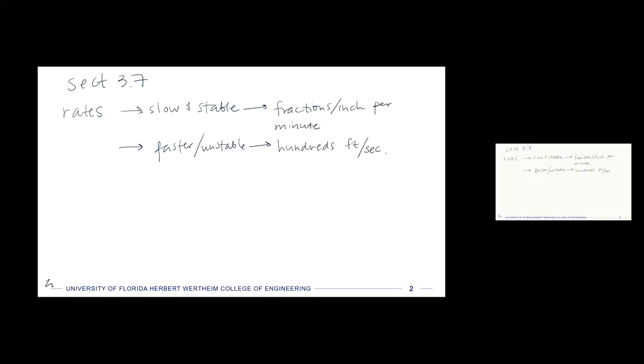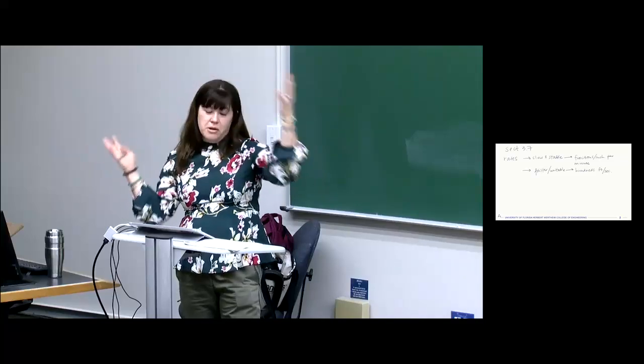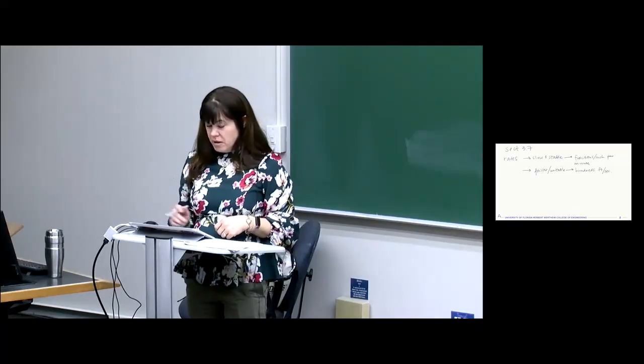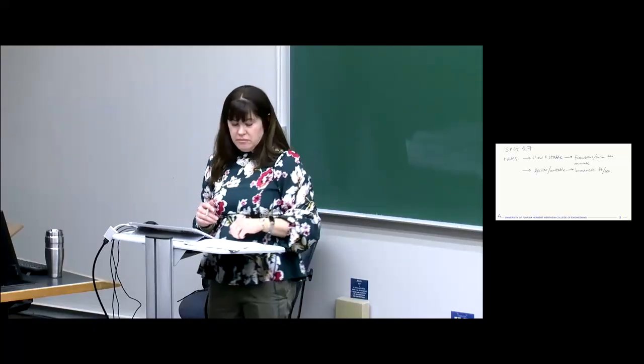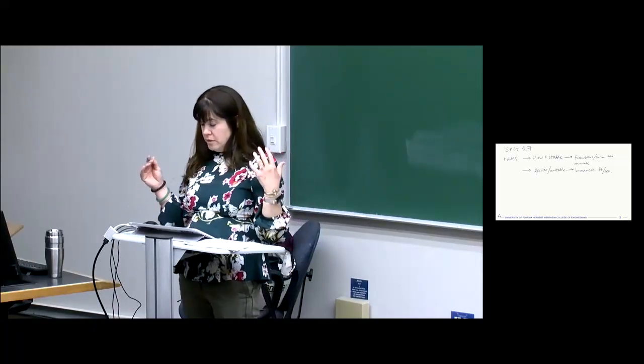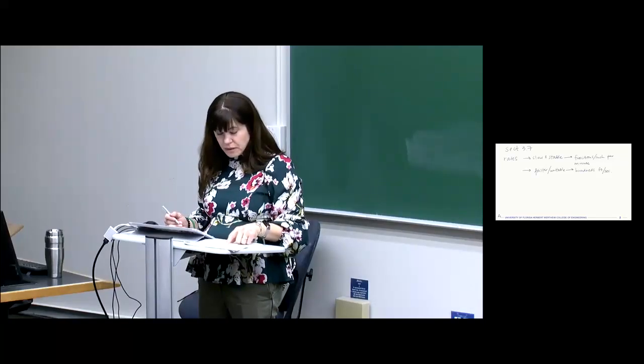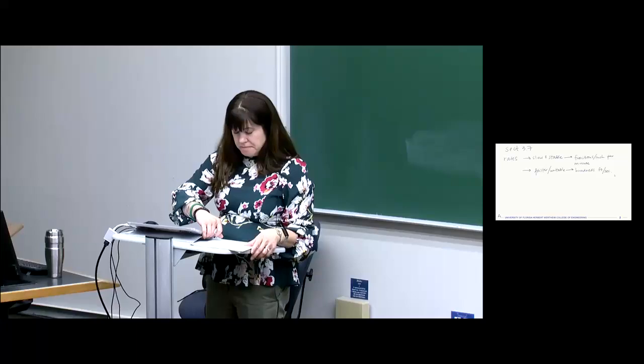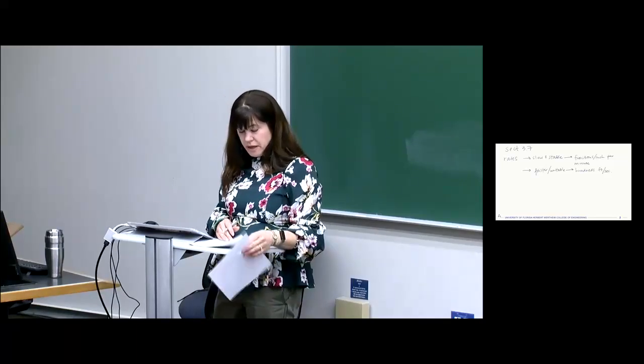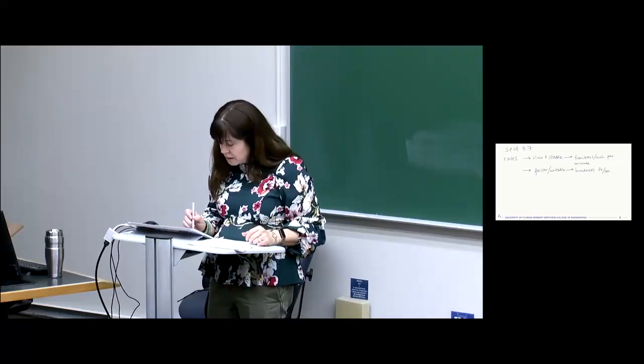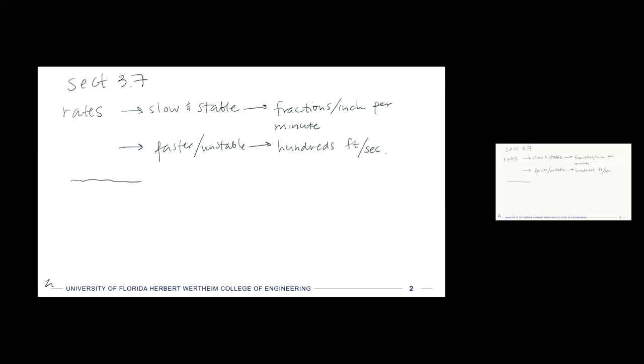When we think about that Comet aircraft, the fuselage broke apart very quickly. It sort of exploded in the air. That was an example of cracks propagating at hundreds of feet per second, sort of too fast for humans to react and save and fix things. These were done in experiments of a notch in a tensile specimen, so I'll just draw that here. If here's our tensile specimen, and we have a load that is manifested as just an axial stress going in this direction.